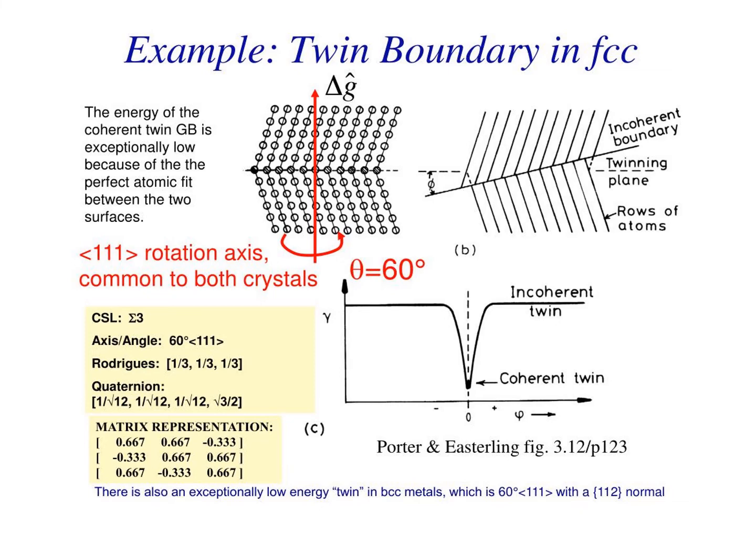This was lifted off the internet, and these authors chose to identify a common rotation axis, which is 60 degrees. What they really should have said is just that it's a 1-1-1 plane along here. This common rotation axis isn't a true rotation axis, it's a rotation axis in projection, and comes about because when you have close-packed spheres, you have this six-fold symmetry.